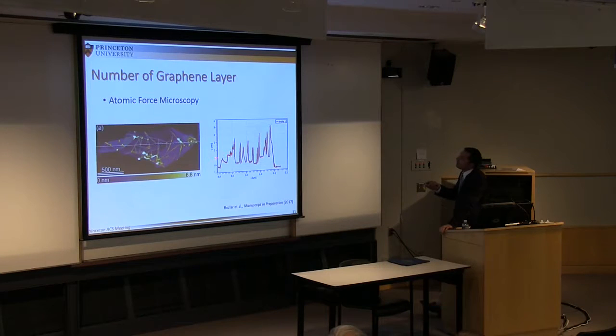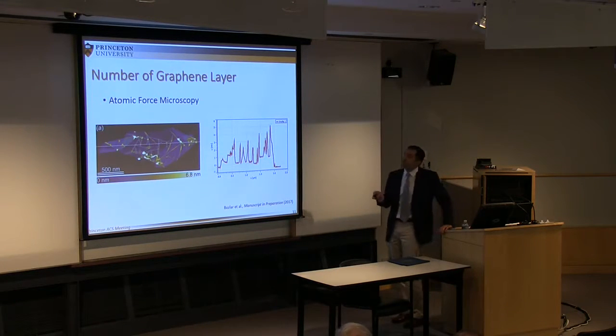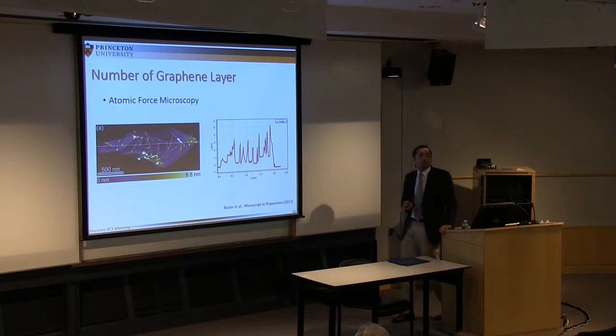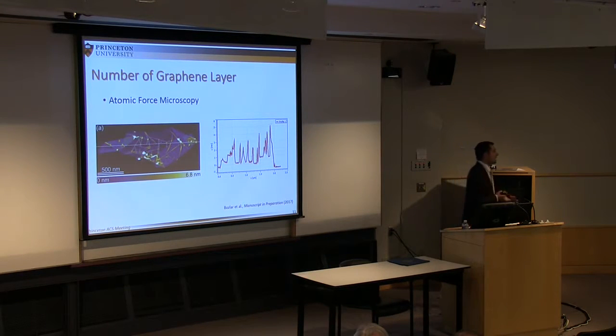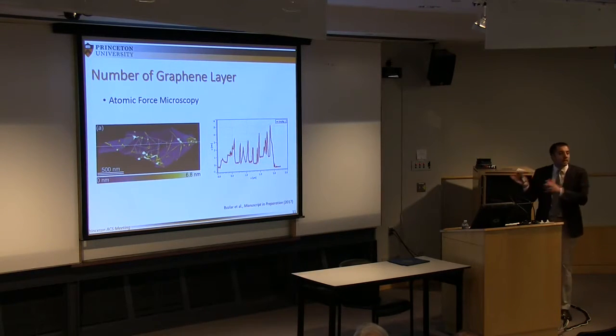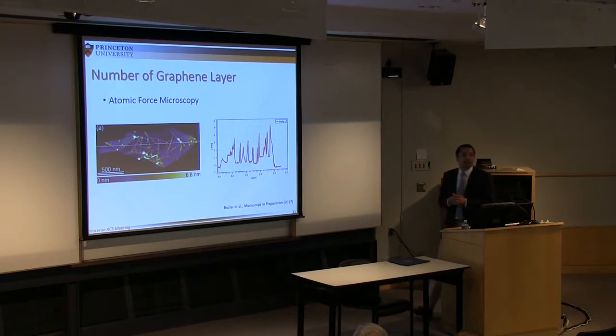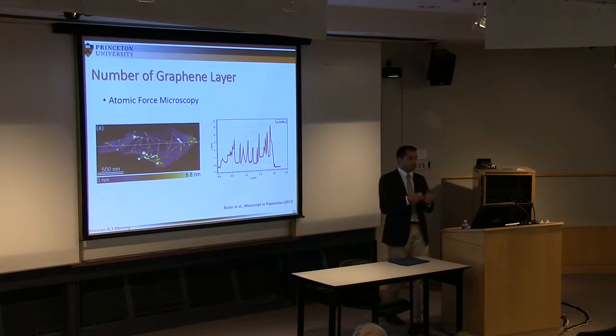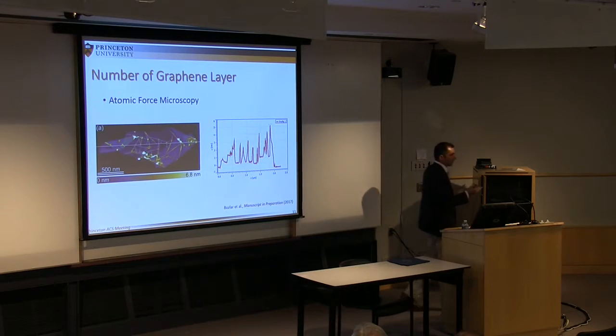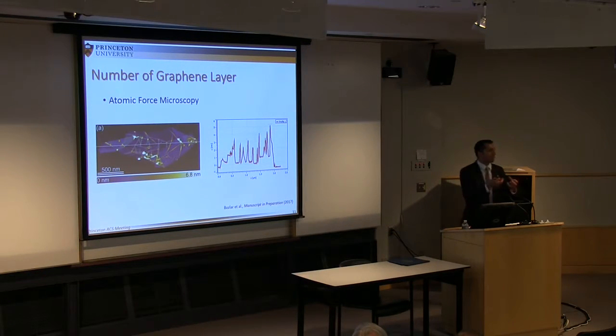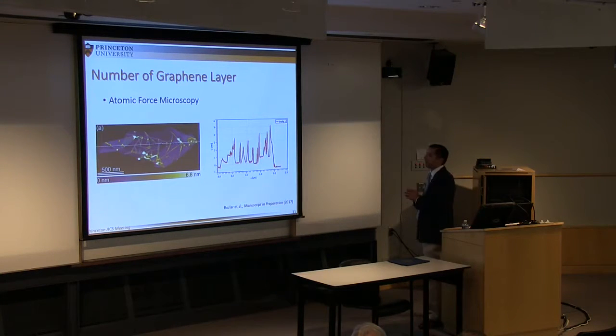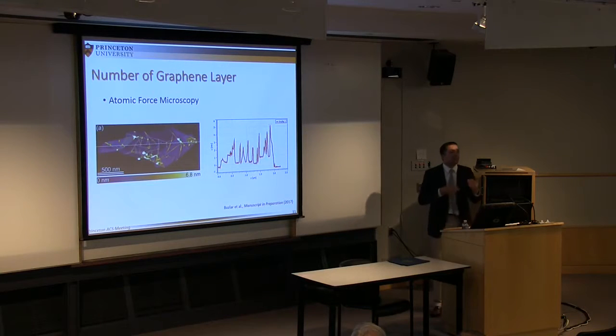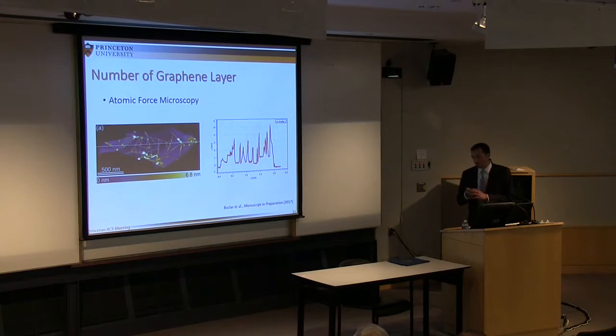And when you look at the height profiles, here you see we are almost at about 1 nanometer, and the functionalized graphene produced here at the university has about 1.8 nanometer height, whereas pristine graphene, the one made by Bozlar from mechanical exfoliation, has a thickness of about 0.7 nanometer. So where is the difference coming from? It's simply coming from the fact that we have functional groups and we have a defective graphene, in other words, in our case. So we'll go to that later in detail. That makes 1 nanometer of difference between the two.